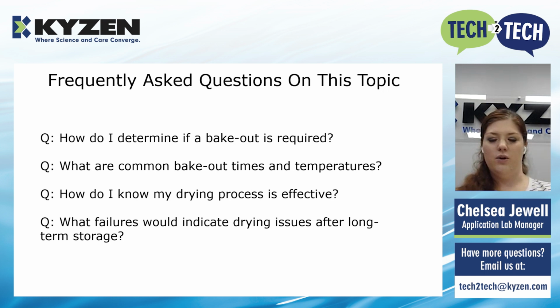I've done testing where we've taken an air nozzle and seen how much water drives out from underneath it, and looked at moisture indicator strips to see whether, once I have that board packaged up, it shows up on the moisture indicator strip. So those are a couple of options that we look at in building out common times. But normally it will be between an hour to 4 hours at least 100 C, depending on how complex your board is.